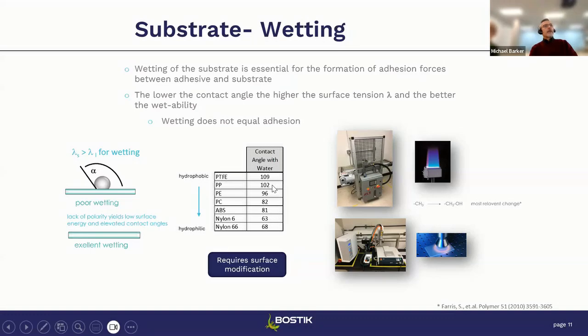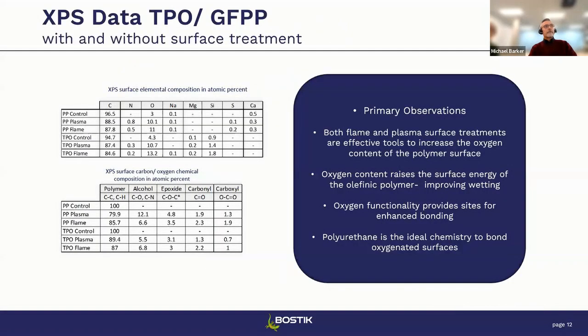So there's a couple of things we can do to introduce oxygen into the surface of the polyolefin. One of them is flame treatment. The other is a plasma treatment. And the literature is very clear on what's happening here. The flame or the plasma breaks the carbon-carbon bonds on the surface of the substrate and inserts oxygen. And that's a very key takeaway. And it's the oxygen introduction into the surface which allows a polyurethane adhesive to bond to it.